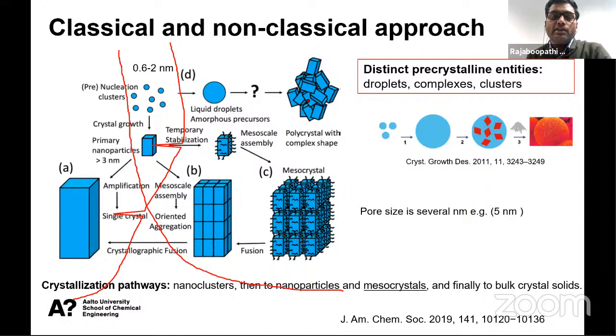So it comes to this hierarchical structure. After the nucleation cluster, the nucleation clusters will attach together to form a bulk liquid droplet, or we can say an amorphous phase. After the amorphous phase, it will densify, or some crystals will appear on the surface of the amorphous phase, and it finally produces a hierarchical structure. So this is the pathway for the hierarchical structure. This is the nucleation cluster. The nucleation clusters will attach together to produce an amorphous liquid droplet, a bulk liquid droplet. After the bulk liquid droplet, there may be some small nanoparticles, and these nanoparticles attach together to form a hierarchical structure. So what is the difference between a mesocrystal and a hierarchical structure?